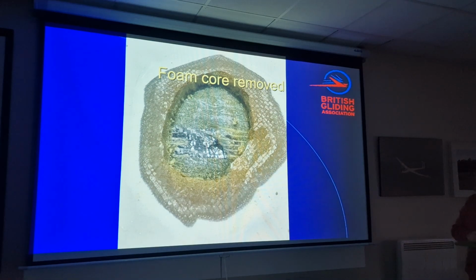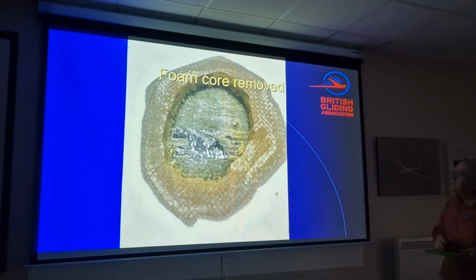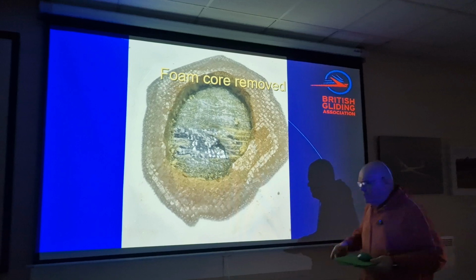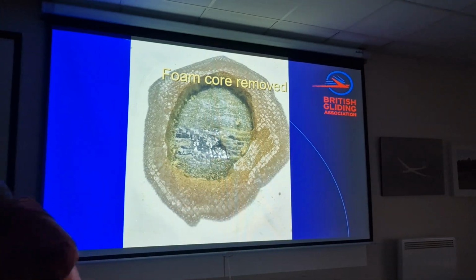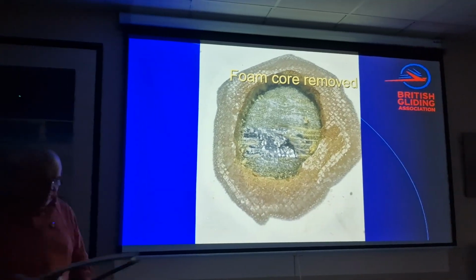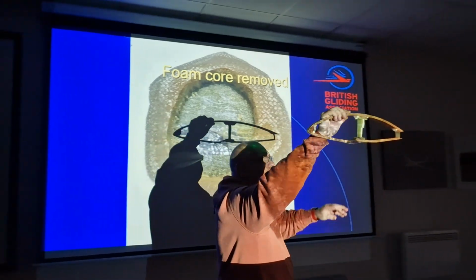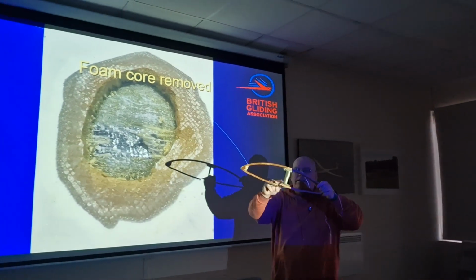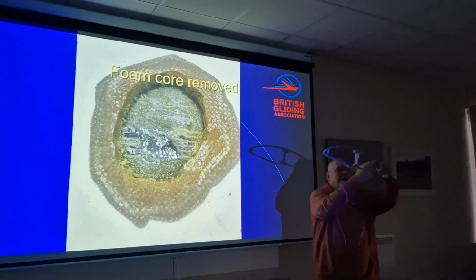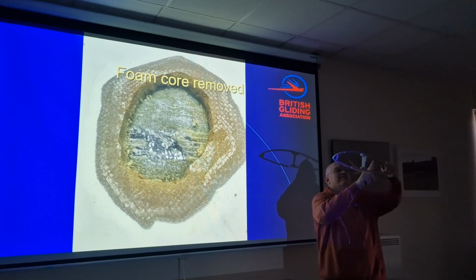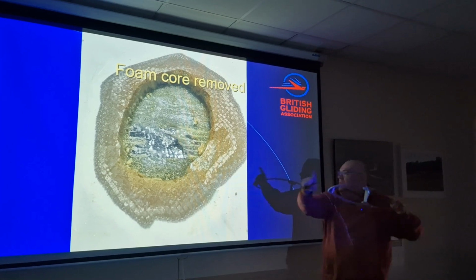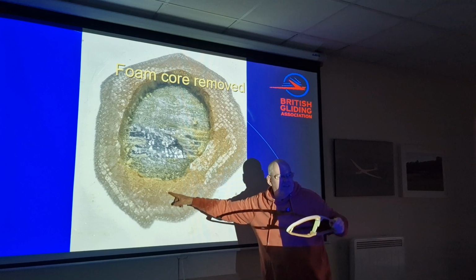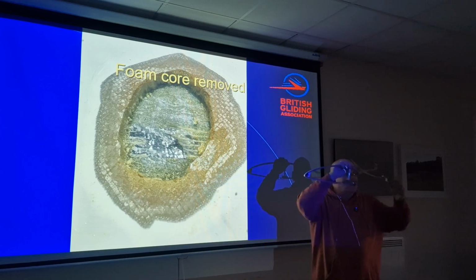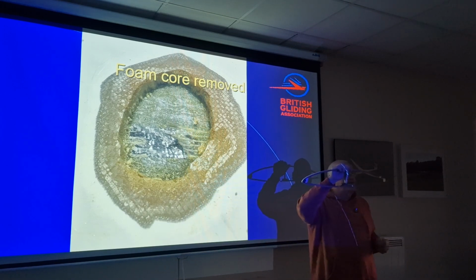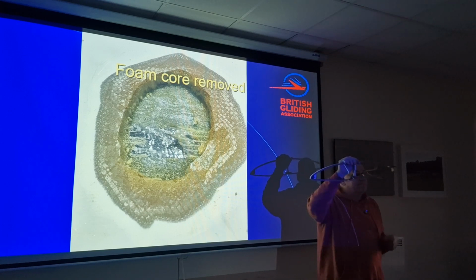Here we have, and Richard Moyse is here, one of his repairs. This is a foam core repair, a bit of an ASW 20 wing. This is literally a sandwich: an outer skin, 8 millimetres of foam, and an inner skin. And this bit here, where the splice is at 30 to 1, is 3 layers of glass fibre, less than a millimetre thick.